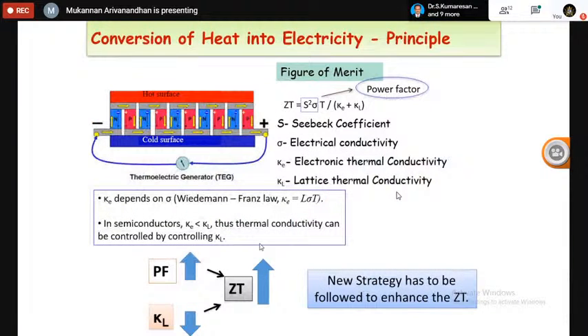Okay, so the performance of a thermoelectric cell can be determined based on the figure of merit. The figure of merit is here. It's the ratio between the power factor and thermal conductivity. And the power factor is nothing but the product of the square of the Seebeck coefficient and the electrical conductivity. From this relation you can understand the figure of merit is directly proportional to the power factor and inversely proportional to the thermal conductivity. So if you want to improve the figure of merit, you have to do this kind of tuning: either increase the power factor or decrease the thermal conductivity.